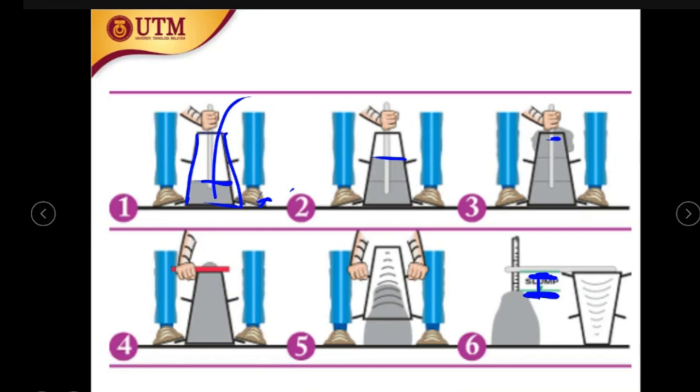Simply put, for normal concrete, which is suitable for building a normal structure, like my house, not a high-rise building, not an offshore structure, not that complicated a structure, the minimum required slump is about 100 mm. According to the design code, it is 75 millimeter plus or minus 25 millimeter. So it is about 100 mm.